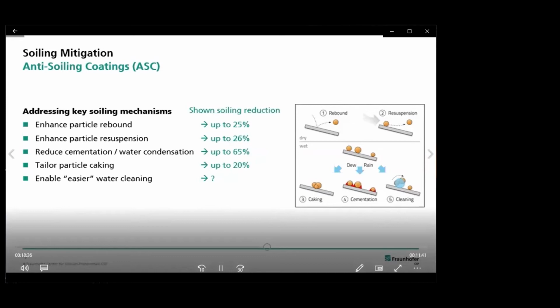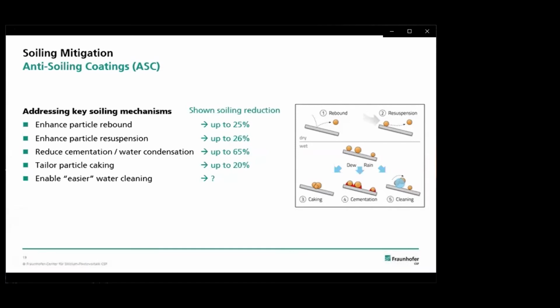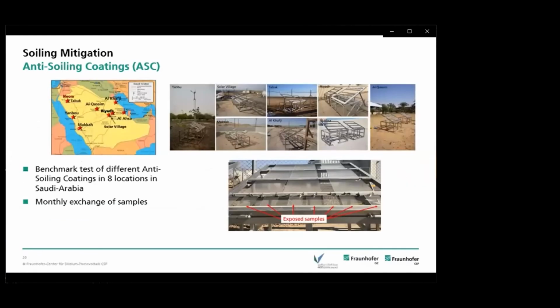And so far we have seen significant reductions for all of these processes in the range of 20–30%, or even when it comes to reducing water condensation and reducing cementation up to 65%. However, these results were also very dependent on the local conditions. For example, we performed an outdoor benchmark test using different anti-soiling coatings and exposing them at 8 different locations in Saudi Arabia. And we exchanged samples on a monthly basis.